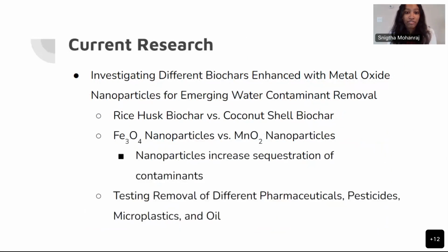And so my current research investigates different biochars enhanced with metal oxide nanoparticles to remove emerging contaminants from our water. I tested different biomass materials, which were rice husk and coconut shells, to see how that affected the results. And then I tested two different dopants. They were iron oxide nanoparticles and manganese dioxide nanoparticles, since nanoparticles can increase the sequestration of contaminants by adding or improving properties of the biochar. And so then I tested the removal of different pharmaceuticals, pesticides, microplastics, and oil, because these are some of the most common and detrimental contaminants that we can find in a lot of water sources.